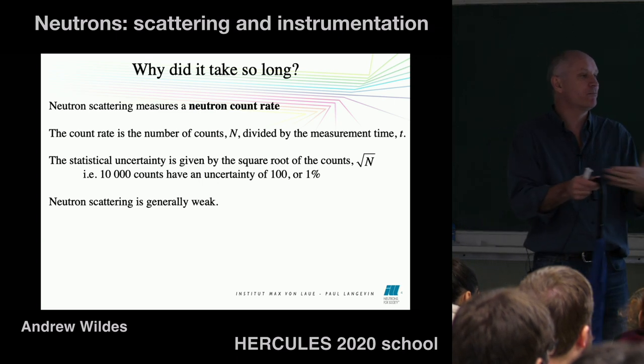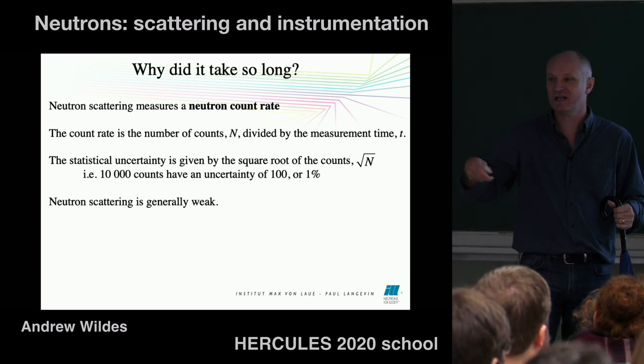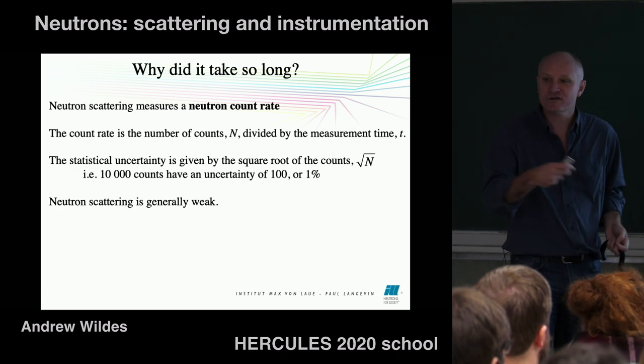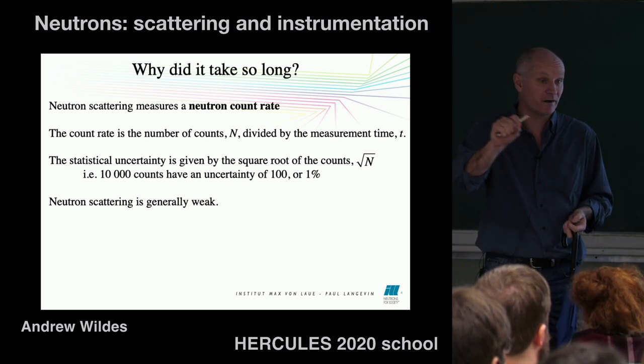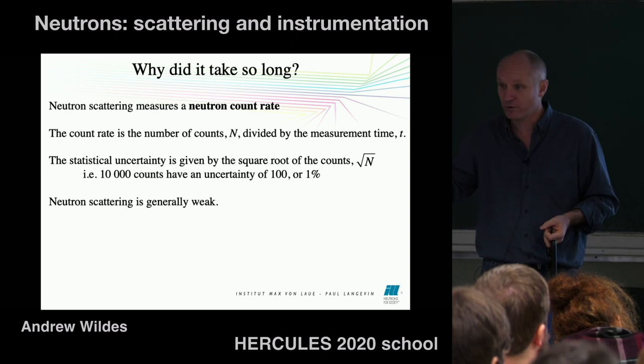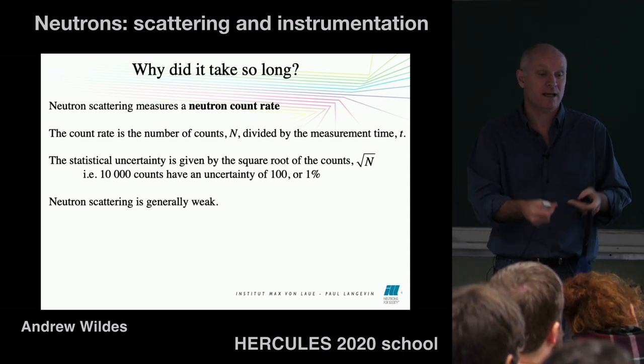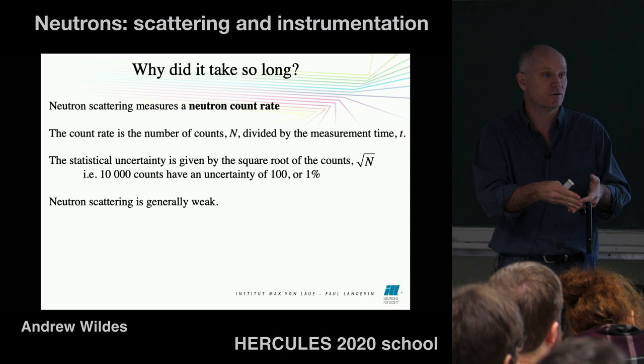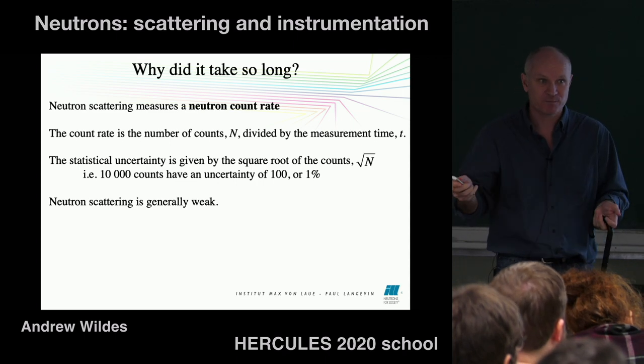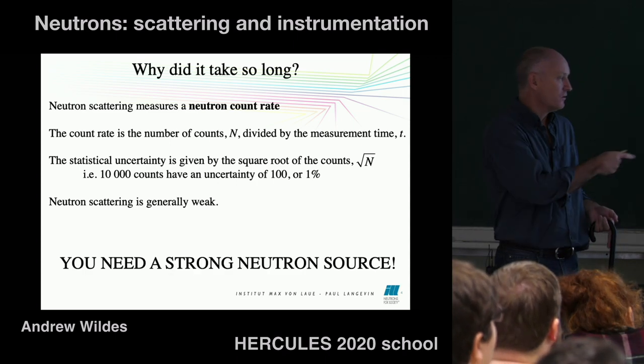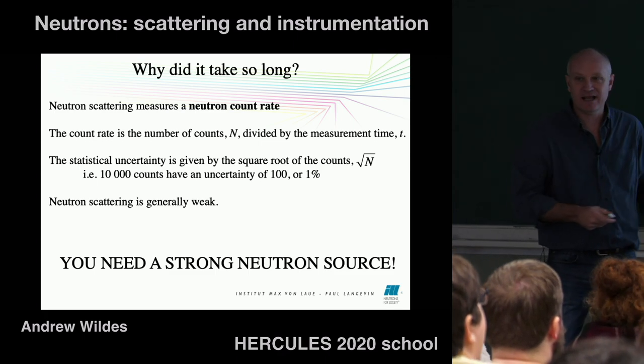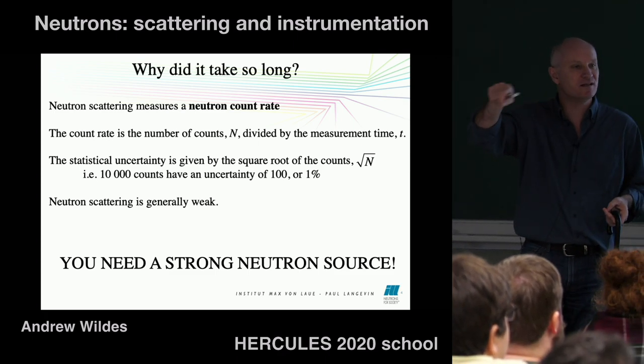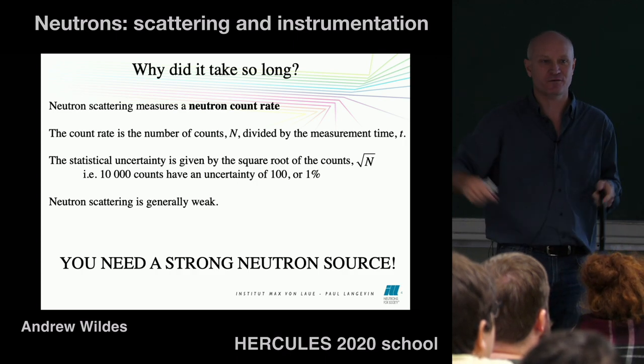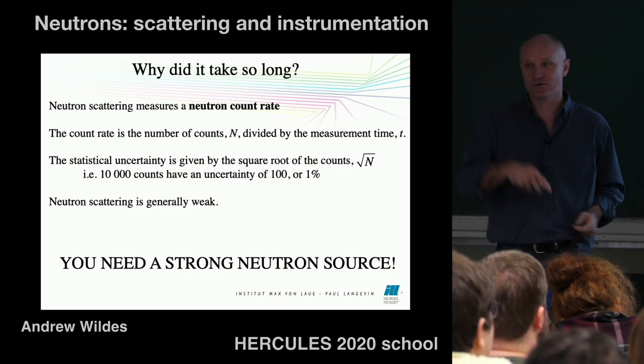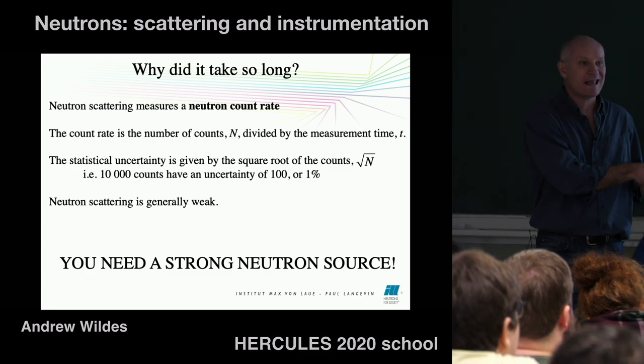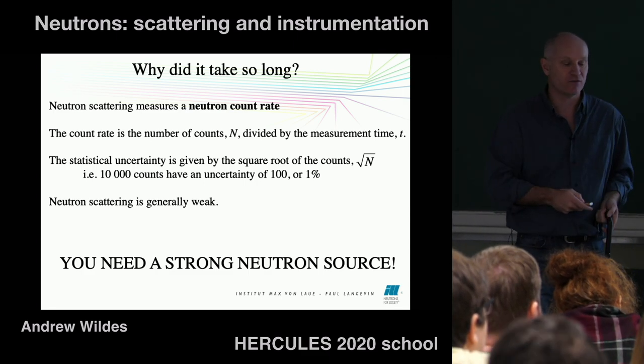Now you might say, all right, I want a precision in my measurement of 1%. You've got to measure 10,000 of these things. Neutron scattering is generally very weak. In fact, that's one of the key things with the first Born approximation in order to get it to work, is the interaction between the neutrons and whatever you're scattering from must be weak. So that's known. So what you really need in order to count 10,000 counts, you might only get a very small percentage of those neutrons that actually scatter from your sample. You need a strong neutron source. And that was really what was lacking in the early days after they discovered the neutrons.